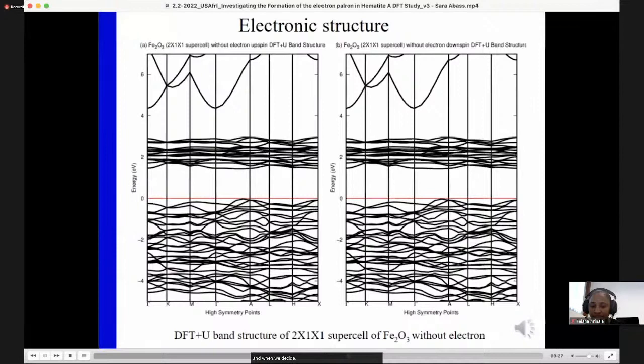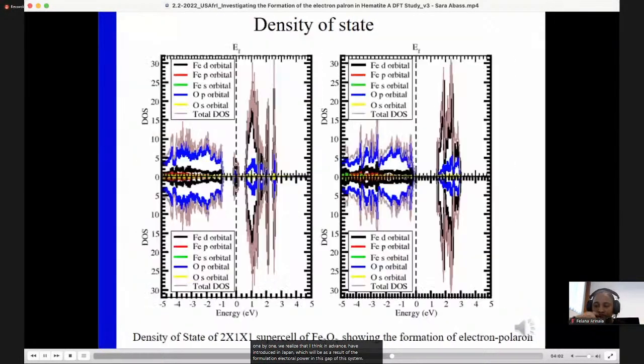And when we decide to look at the supercell of the hematite structure, we start with a 2 by 1 by 1 supercell. We look at the band structure of this material without an extra electron and are able to see the band gap. And when we add an electron to this 2 by 1 by 1 material, we realize that a single band is introduced in the band gap, which is a result of the formation of an electron polaron in the gap of this system. When we go further and look at the density of states of the 2 by 1 by 1 supercell structure, we see the formation of a state in the gap, which also shows the situation of the electron polaron in this system.